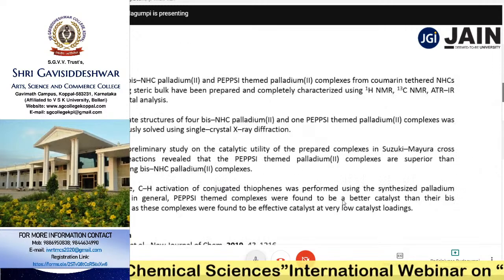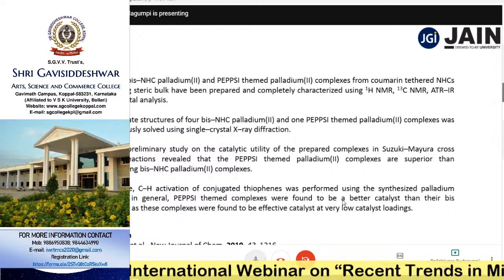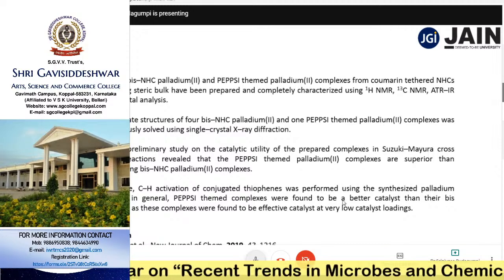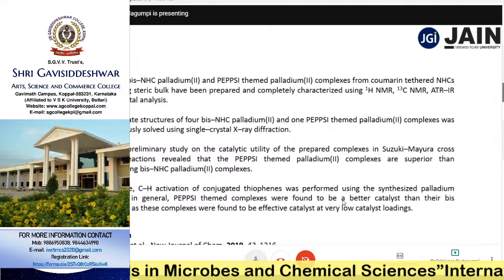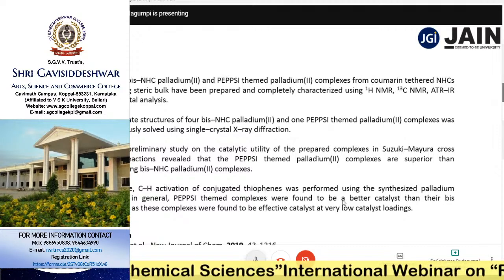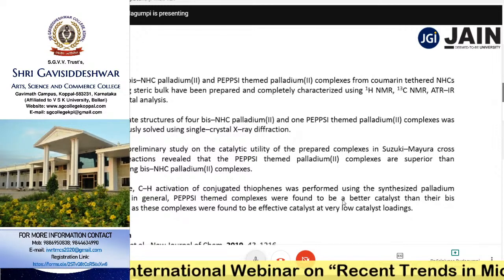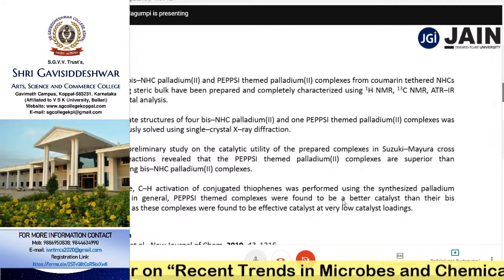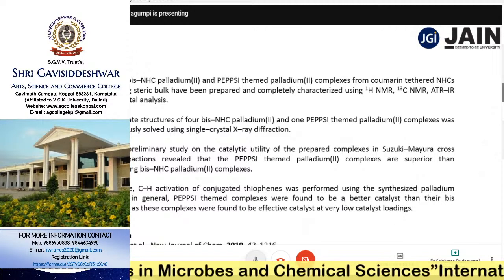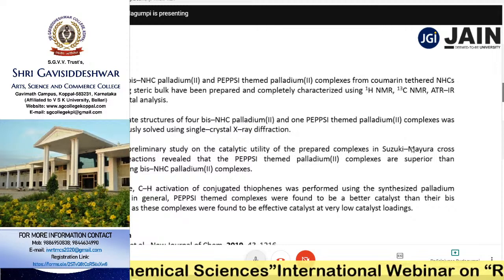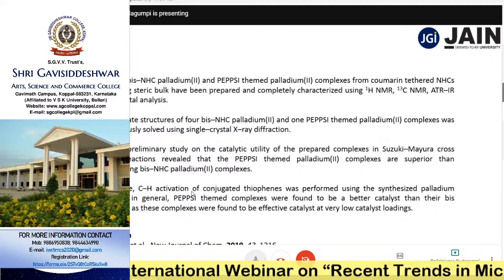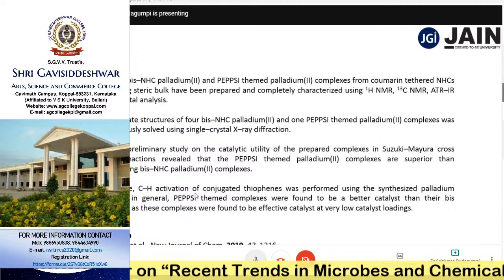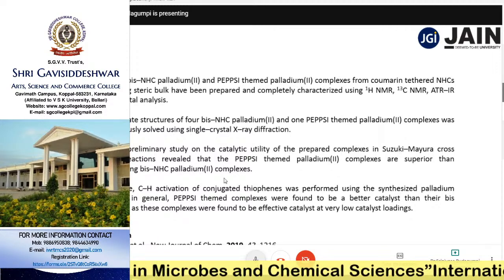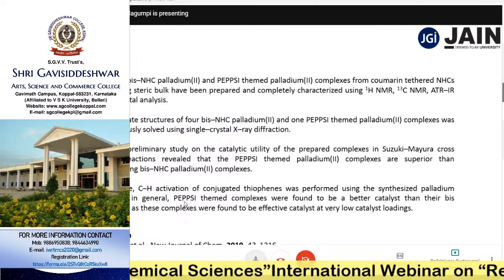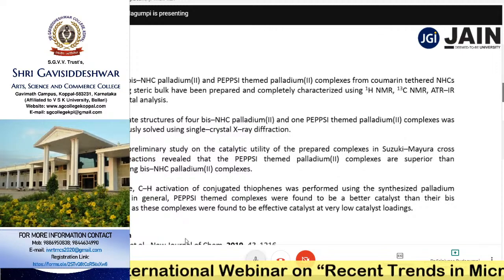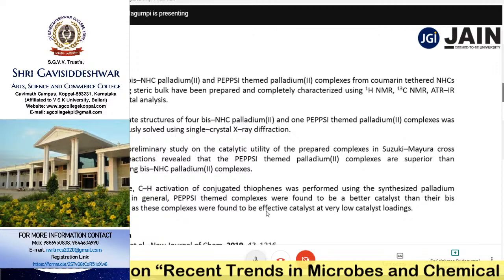In summary, a series of palladium bis-NHC coordinated and PEPPSI-themed palladium complexes have been prepared, which have NHCs substituted with coumarins, and all the characterizations were done using spectral and elemental analysis. Solid state structures were established using single crystal X-ray diffraction. It is evident that in both the Suzuki-Miyaura cross-coupling reactions as well as the C-H activation reactions, PEPPSI-themed complexes showed better activity than the bis-NHC complexes, because of the presence of the labile pyridine ligand. We could publish this work in New Journal of Chemistry and Journal of Organometallic Chemistry.